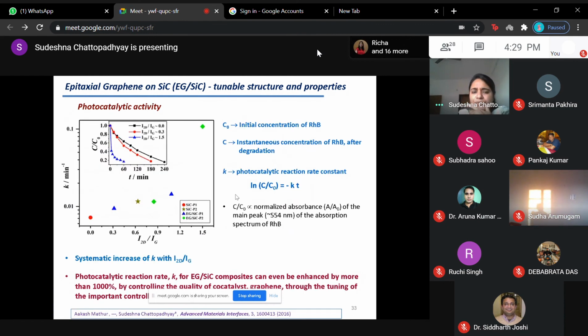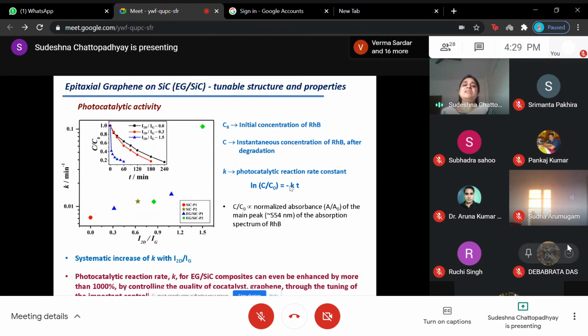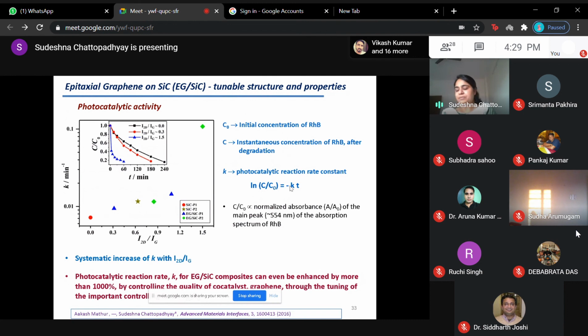Now for a different I2D by IG, if we plot, we can see that K is the parameter which quantitatively tells how the photocatalytic reaction has been enhanced. You see that K is increasing when your I2D by IG is increasing, in a really nice manner. And then we have plotted C by C0 also, how it is changing, and this is in the log scale.